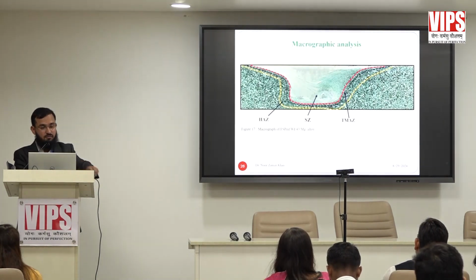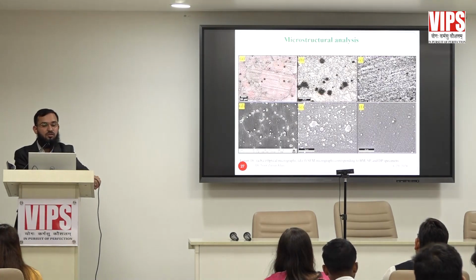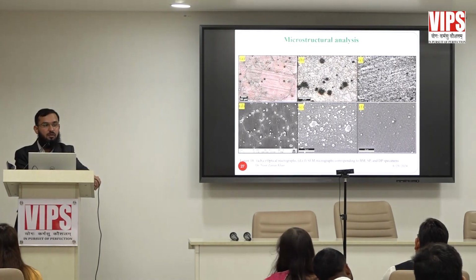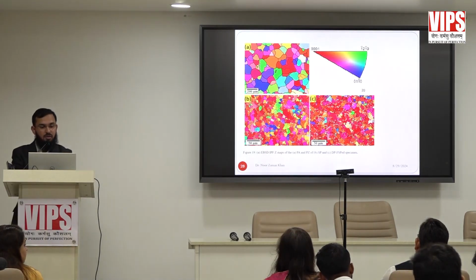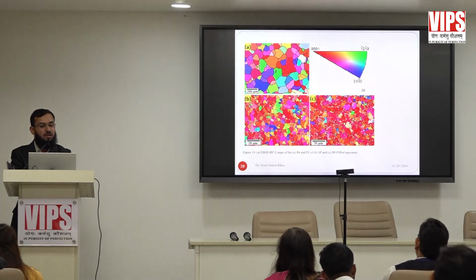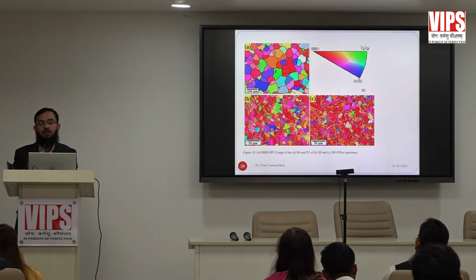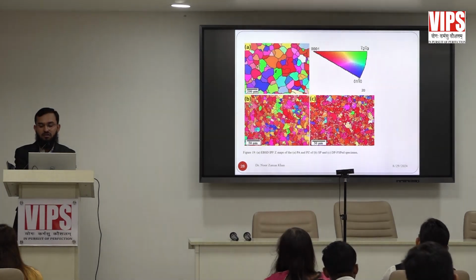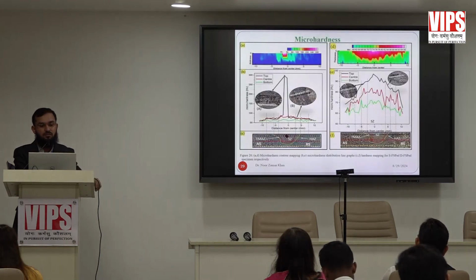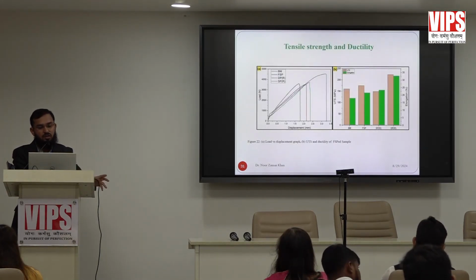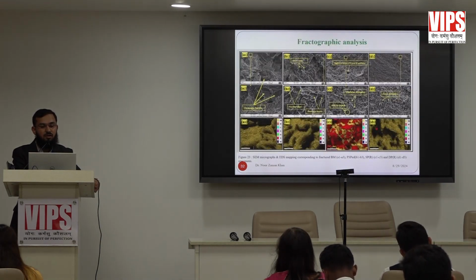Case study. Okay, I'll move. If you see the microstructure, figure A is the base material microstructure, and B and C are the friction stir processed microstructure. You can see the difference in the grain size. If you see this EBSD, you can see the difference in the grain size. A is the base material, the raw material, and B and C are the material after friction stir processing, or you can say after severe plastic deformation. The drastic reduction in the grain size means we can enhance the strength. Micro hardness, tensile strength: you can see the base material tensile strength, and you can see the tensile strength after processing.